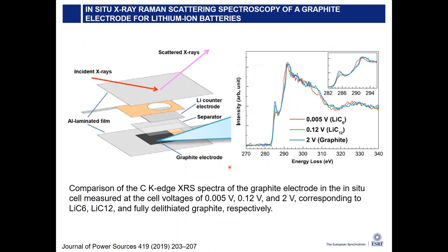And this is interesting if you want to do research in batteries, for example, where in this case, you look at the carbon in this battery setup. So this is an in situ experiment. You see there are several windows, there's a graphite electrode, separators, and the lithium counter electrode. And then different voltages are applied, and the carbon inside the sample changes depending on the voltage. And I can nicely measure in situ the changes of the carbon chemical environment using this X-ray Raman spectroscopy.